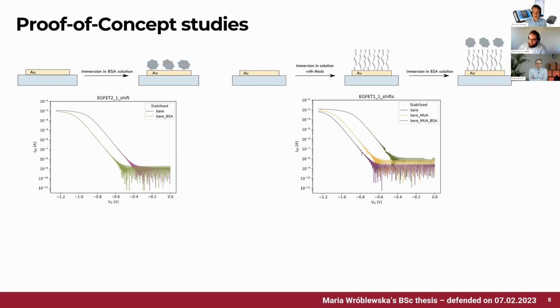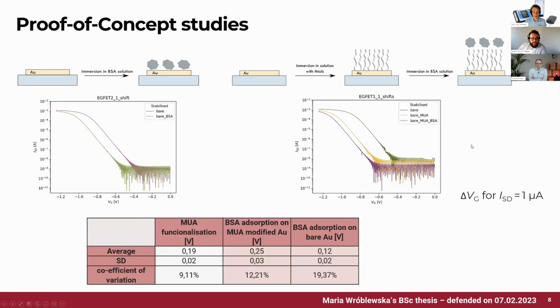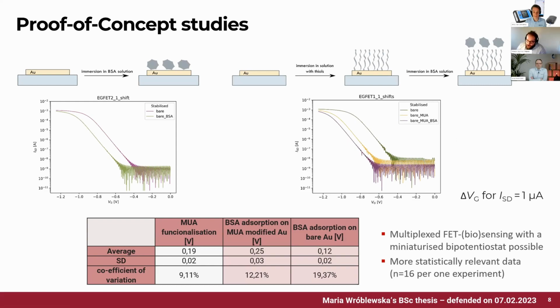All right, great. And now we have slide 8 open anyway. We see a bit of noise on the right end of the graph. Could you explain what it is? Yes, so all the measurements apart from the slide with the Faraday's cage were done without the Faraday's cage. That means that we pick up some 50 hertz noise, and this is rather difficult to eliminate without the Faraday's cage, obviously. But it's still feasible for measurements of extended gate field effect transistors. What we do here is we can simply interpolate this subthreshold slope with a function, and then the noise is not relevant to our whole curve shift. Exactly. Yeah, no, that's great.